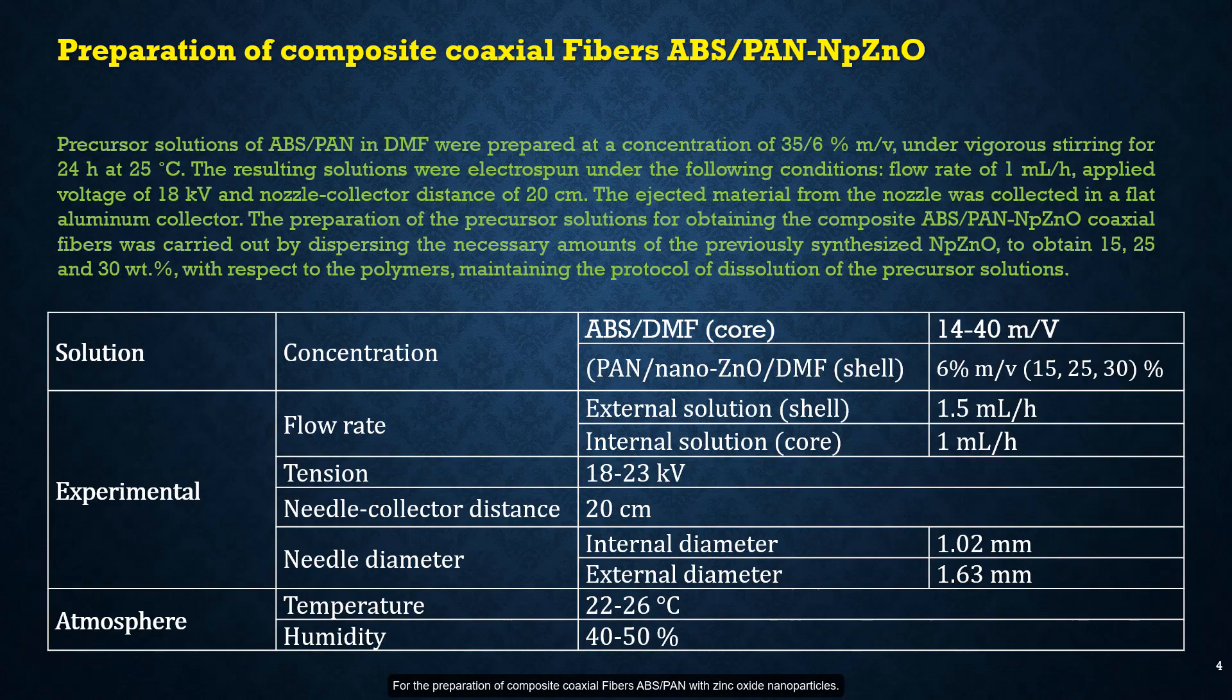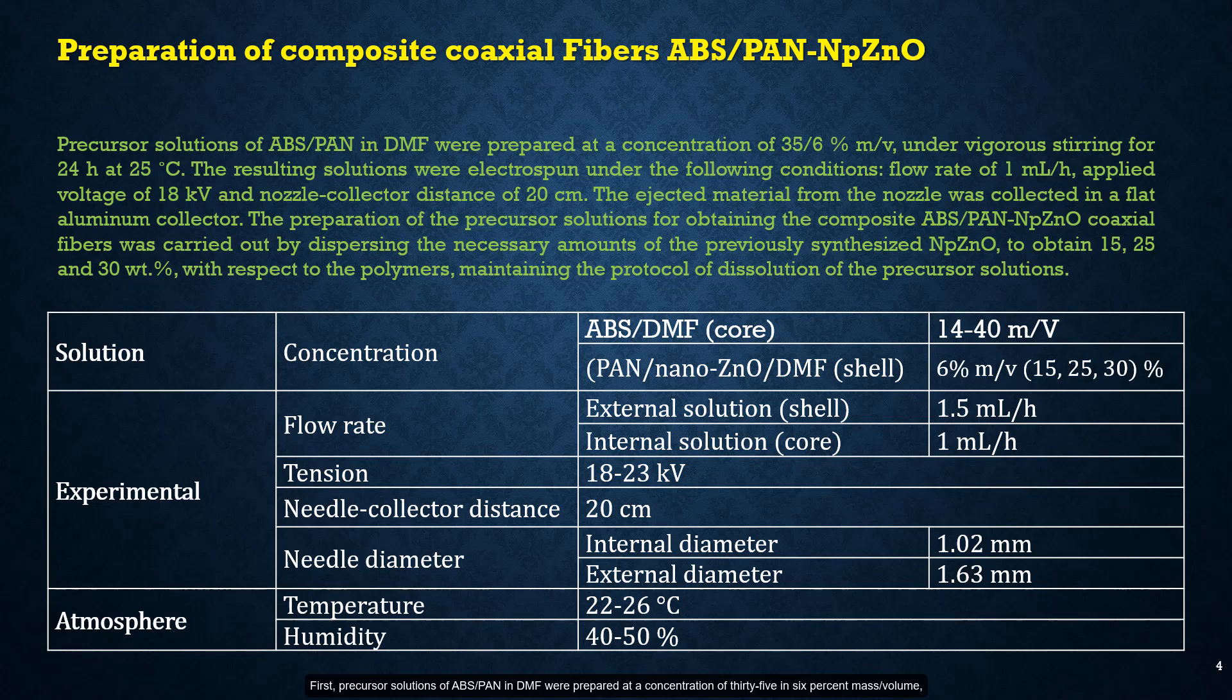For the preparation of composite coaxial fibers of ABS polymer with zinc oxide nanoparticles, first precursor solutions of ABS polymer in DMF were prepared at concentrations of 35 and 6% mass volume under vigorous stirring for 24 hours at 25 degrees Celsius. The resulting solutions were electrospun under the following conditions: flow rate of 1 ml per hour, applied voltage of 18 kilovolts, and nozzle-collector distance of 20 cm.